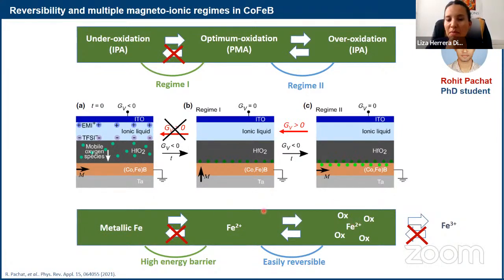And then this is probably why this process here is easier to reverse. It has a lower energy barrier to bring oxygen back and forth between these two states than here, because here you really have to convert iron 2 into metallic iron. I'm not saying it cannot be done. It's just that it will not happen at the same gate voltages. So here we're limited by the voltage we can apply, and with the same voltages that we use for reversibility here, it's clear that if this is the case, it will not be possible.